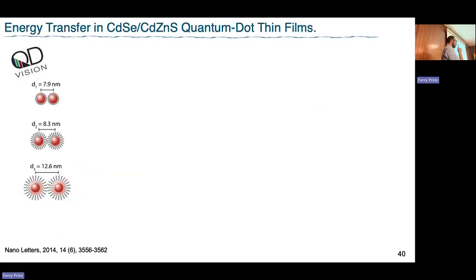Okay, this is an early study, but I think it's a very good example. So here we have these nanoparticles - cadmium selenide. And what we know is that there's excitons there, and an exciton in a nanoparticle, if it hops to the next one, it's going to be energy transfer. So this is a Förster-like process - Förster energy transfer. What is important is the distance between the dipole that you have here and the dipole that you have there. So it's the distance between the center and center of the particles, and we can change the chemistry a bit to control that distance.